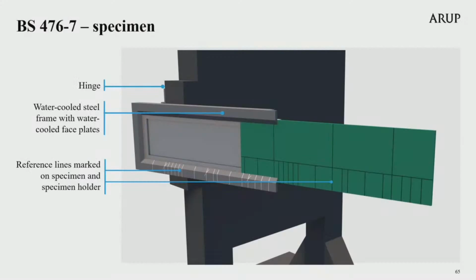When the product is of insufficient size to allow the specimen size to be achieved in width or length, it is permissible for small pieces of the product to be placed adjacent to each other to obtain the required dimension, providing that an essentially flat surface can be achieved. And it is considered in the test standard that such a procedure does not have any influence on the surface spread of flame, but the use of such specimens shall be reported. The specimen holder comprises a water-cooled steel frame with water-cooled faceplates. The faceplates overlap the specimens by 20 millimetres on their top and bottom edges and over the vertical edge adjacent to the radiation panel. A spring-loaded clamp is positioned to clamp the specimen against the water-cooled faceplates. The water supplied to the specimen holder is such that the maximum temperature does not exceed 35 degrees Celsius at the outlet from the specimen holder.